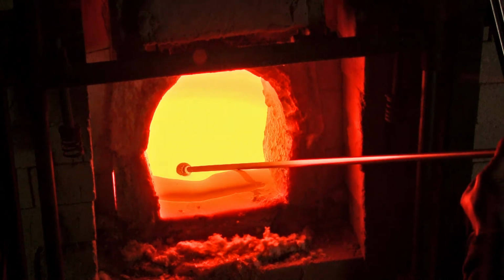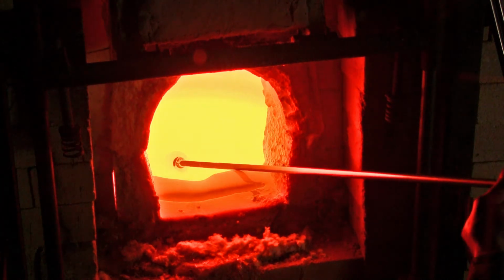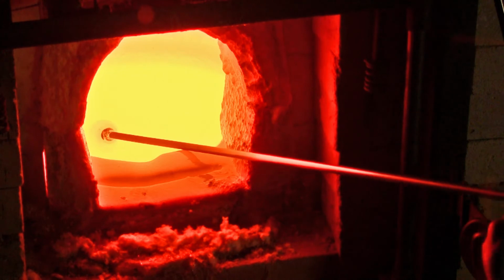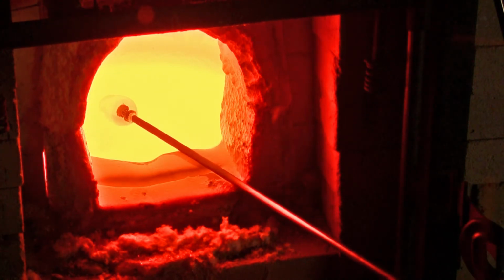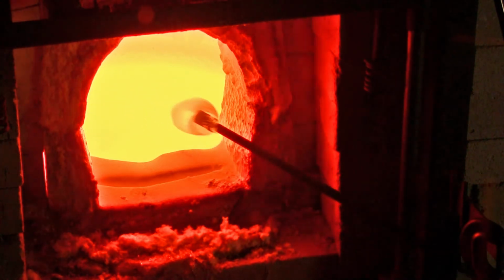To make a bulk gather, we start by pushing the iron near vertically into the melt, making one full turn as before. Then the back end is lowered, and as we speed up the rotation, push it across the surface to form a wave, which is gathered up around the gather as we tail off. For good bits, the fresh mass of molten glass needs to be rapidly pulled off the iron to prevent the core becoming chilled. This can be done with the marver or the block, or by shaking the iron side to side directly after leaving the furnace.